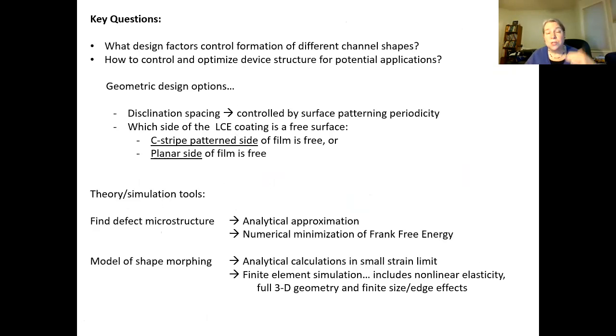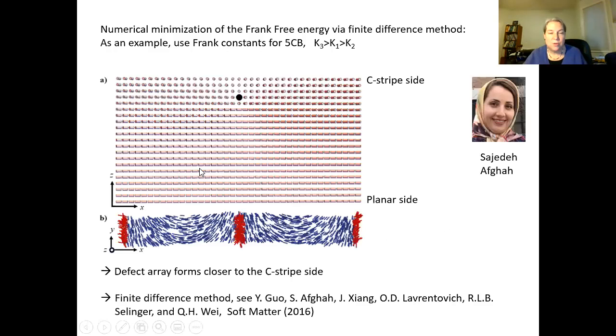And then once we know the director field, then we can put it into our finite element simulation. And from the point of view of the experiment, they had two options. They could take the glass off that was the pattern side, or they could take the glass off that was the uniform planar side. And they got different structures both ways. And they're like, why? Again, you see an experimental colleague and they're like, what does my experiment mean? Why is it doing this? And so the simulation tools can answer some of those questions.